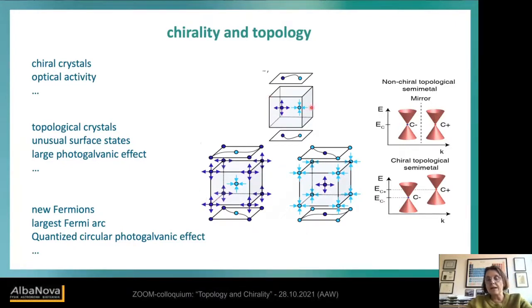If you compare normal Weyl semimetals with these chiral new fermions, we now have the Weyl points at different energies, which gives us a bigger range of energy where we can play around with properties. And we have Fermi arcs which go all over the Brillouin zone, connecting one Brillouin zone to the other. And if we have two enantiomers, they are chiral, they behave like not only in the crystal structure, the crystal behaves like its mirror image, it's also in the electronic structure.